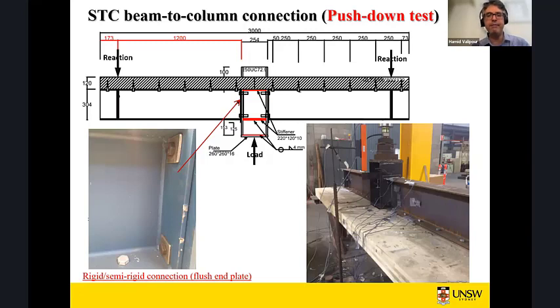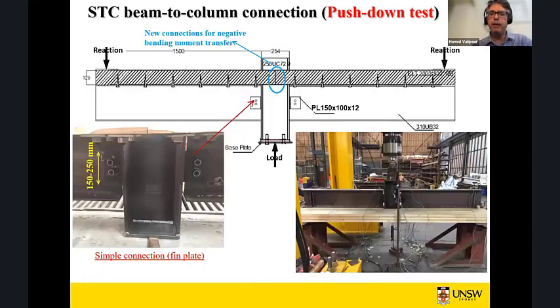And from there, we can evaluate the structural performance of beam to column connections. We look at flush end plate, let's say shear tabs, web cleats, a variety of different beam to column connections, and that's the setup we use. Typically, we flip over the whole specimen, we apply the load at the middle, and then we have reactions upward, which creates the same effect as doing the direct push down test.